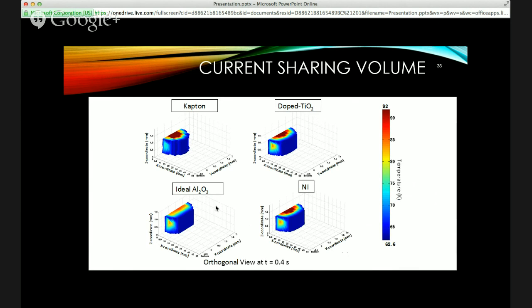However, if you look at doped titania, which has a higher thermal conductivity, as well as alumina in the non-insulated case, it tends to be more distributed between the different layers, especially in the ideal alumina case. You can see that the temperature area is barely around the 90 range, which is a good thing. So it does make an argument for that thermal conductivity piece.